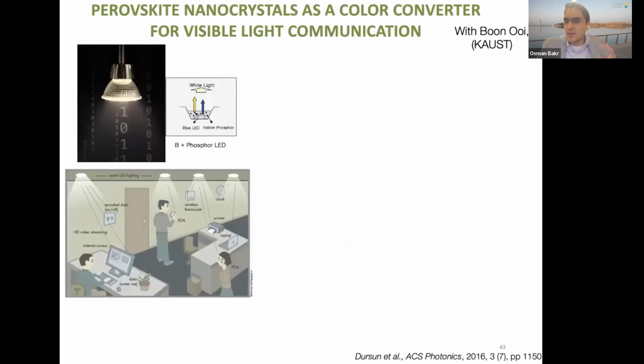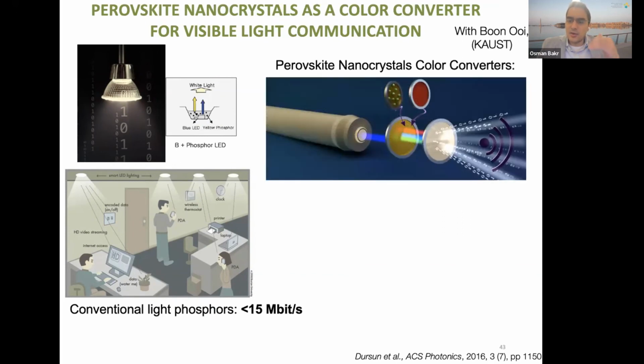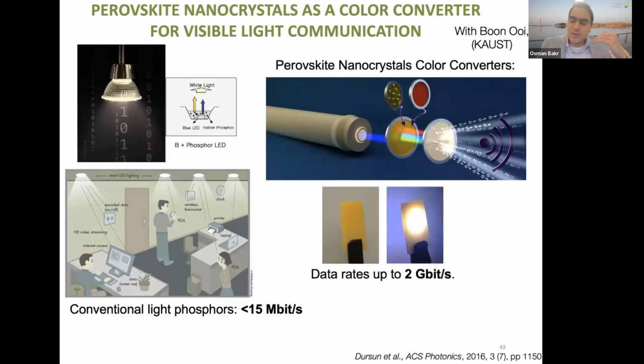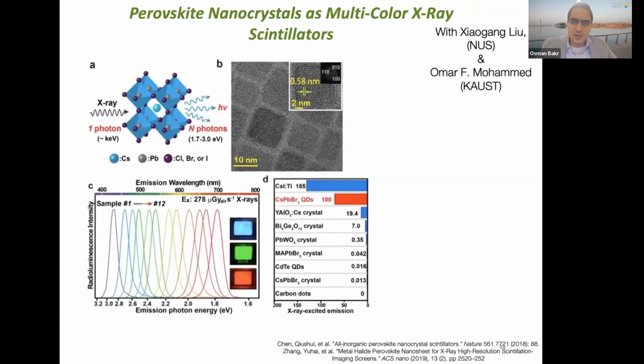And then the final thing, I just want to tell you something exciting about perovskites that's kind of different from most materials. Because perovskites have very good luminescence properties, they also have a very short photoluminescence lifetime at the same time. That means you could apply them in applications where you can modulate light at very fast rates. One of these applications is transmitting data using white light. We showed that perovskite nanocrystals can be used as phosphors for white light data communication, and we could reach gigabits of data communication using white light, which was a record for this technology.